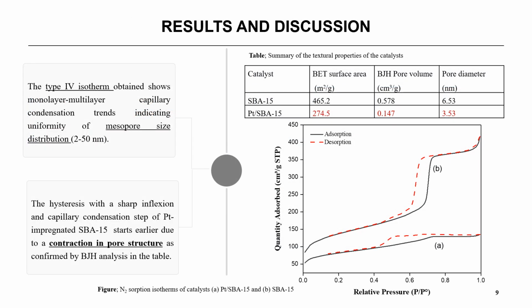Moving on to the results. Firstly, the characterization of the catalysts, as mentioned earlier, was done using XRD, XRF, and BET analysis. From the nitrogen sorption isotherms as shown, it is seen that both SBA-15 and PT-SBA-15 catalysts show monolayer and multilayer H1 hysteresis type 4 adsorption trends typical of mesoporous materials.